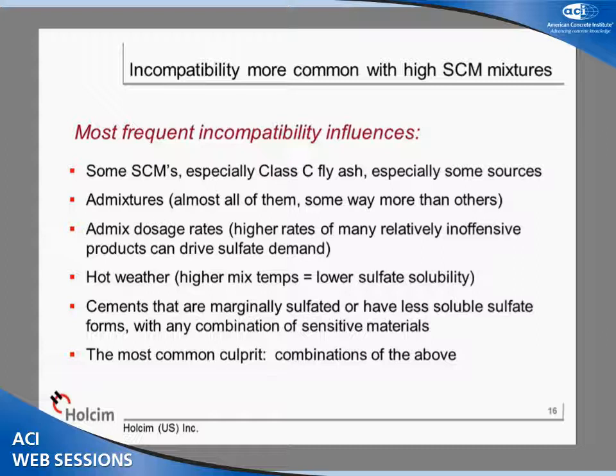Certain admixtures, almost all admixtures, have some bearing depending on the dosage rate. Certain admixtures more so than others. And as we get into multiple admixtures, these questions become infinitely complex. Hot weather is another incompatibility influence because the solubility of calcium sulfate changes in an unexpected way. As temperatures get warmer, solubility actually becomes more difficult for calcium sulfate in solution.